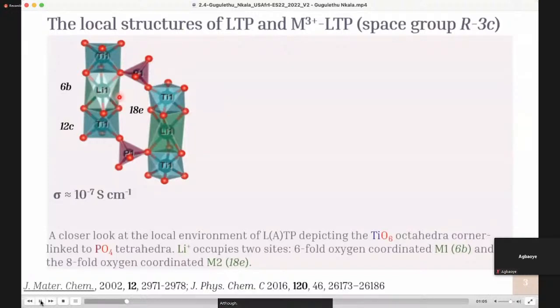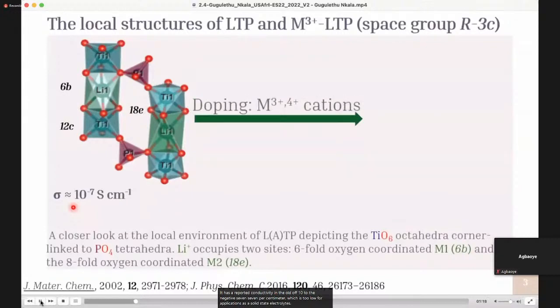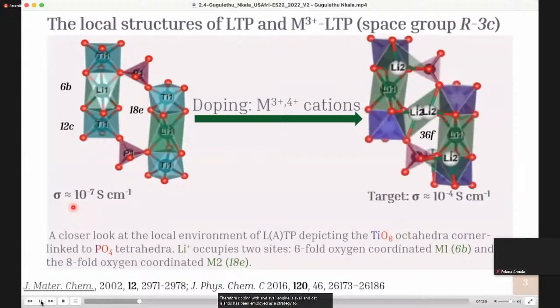Although this structure can allow for fast ionic migration, it has a reported conductivity in the order of 10 to the negative 7 Siemens per centimeter, which is too low for applications as a solid-state electrolyte. Therefore, doping with aliovalent and isovalent cations has been employed as a strategy to improve the ionic conductivity of LTP.